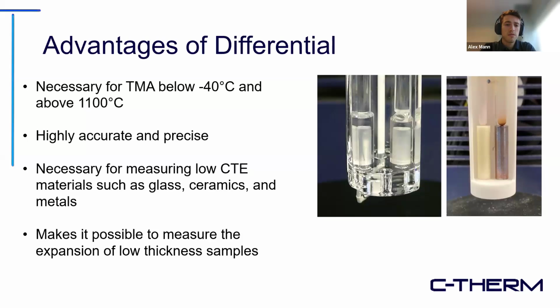And then quartz softens around 1100, so we can't really use it anymore, meaning that now we have to use alumina for our sample holder. As we can see here, we have the differential with alumina on one side, and this side is quartz. Alumina has a CTE of around 5 ppm, or roughly 10 times more than quartz. This means that the error we get will be around 10 times more. And also, only materials that go above 1100 are metals and ceramics, which generally tend to have lower CTEs. This is why you absolutely need the differential method to cancel out the expansion of the holder, the support pipe, and the detection rod.